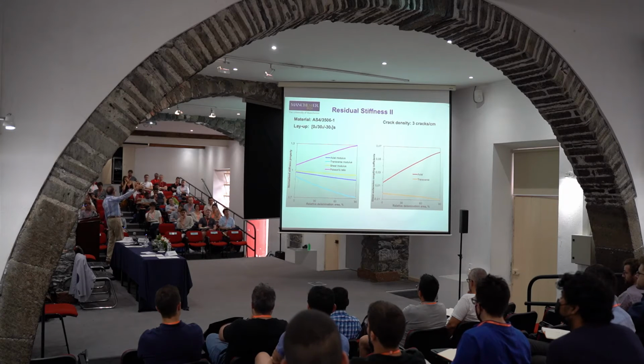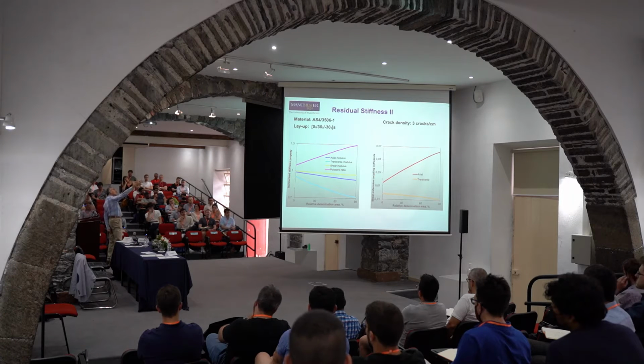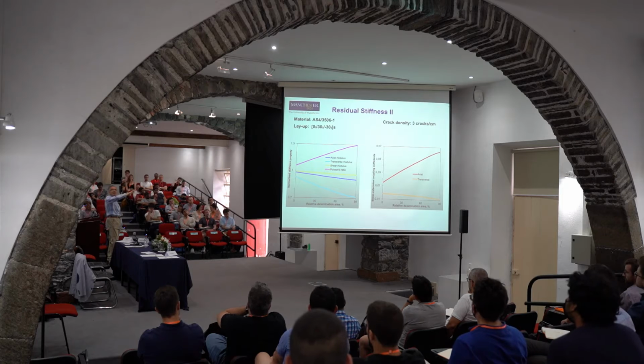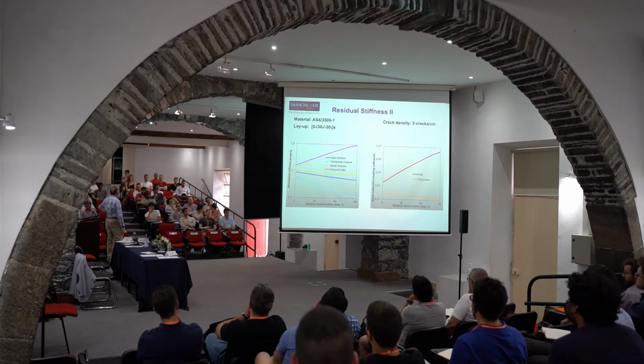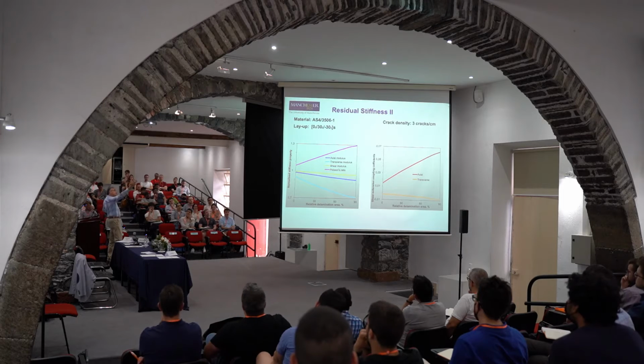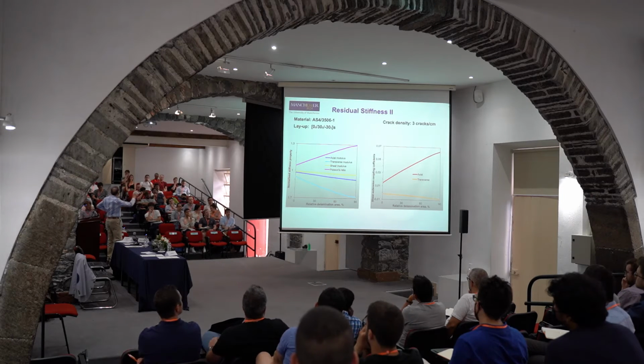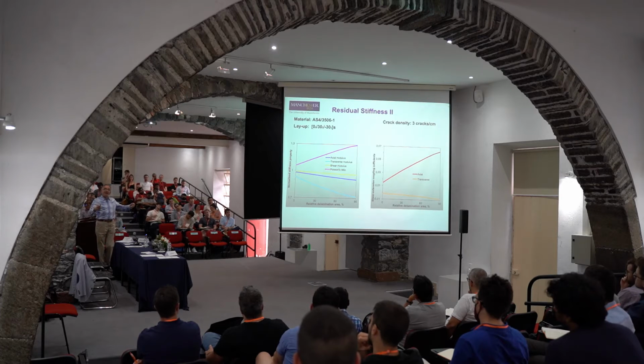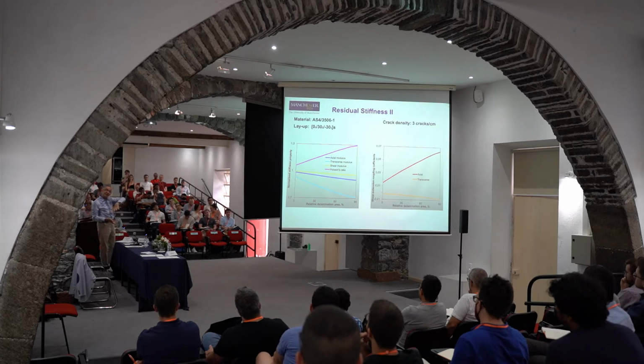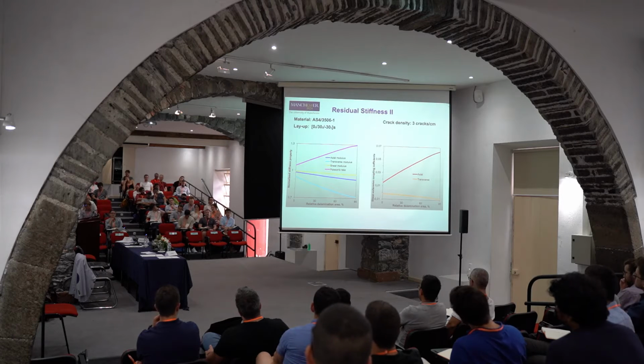So with this configuration, in an anisotropic plate, like say, 0/30/minus 30 symmetric, how many layers do I have in that laminate? I have 2, 4, 6, 12. Thank you. And I have cracks in the plus 30 and minus 30. I have 3 cracks per centimeter. And I have an amount of local delamination we've seen earlier. So obviously, you apply 1% strain in this direction, and the Poisson ratio changes, increases instead of reducing, because you don't know how this construction is going to move. You need to calculate it. You need to run those equations.